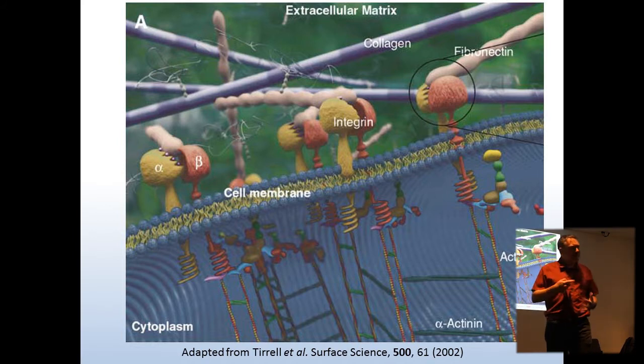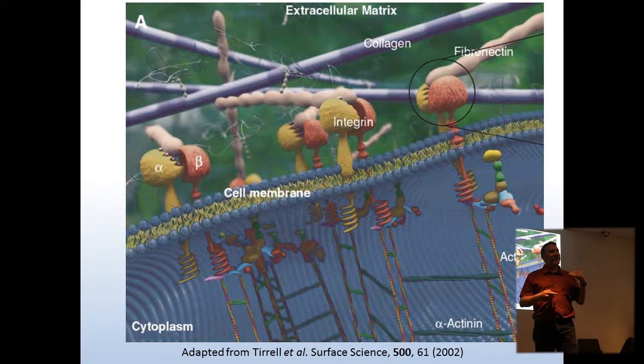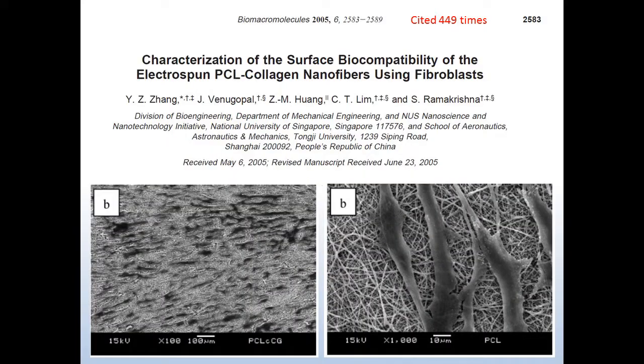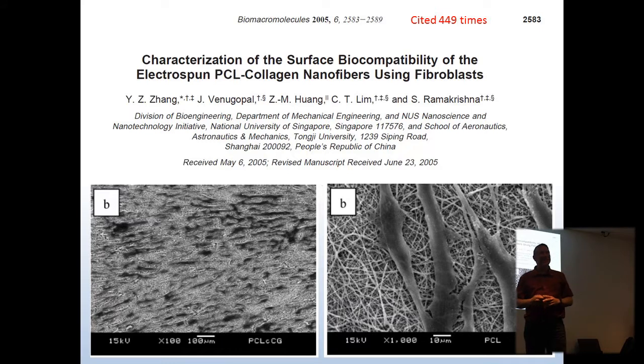But I think one of the things that was missed a little bit early on is that it has a similar size, but the density is completely different. So very early on, if you really look at these substrates that are made, the cells are just sitting on top of the electrospun fibers. There's not much space between the fibers for cells to grow and penetrate. But that didn't stop people from saying that these are cell-invasive scaffolds. Even if part of a cell could get into the membrane, they would say this is cell invasion. I would disagree. Dima would disagree as well. And so this differential between the collagen in the natural ECM and the fibers that we're producing by electrospinning wasn't really talked about until